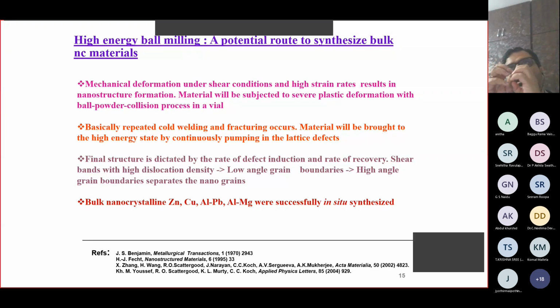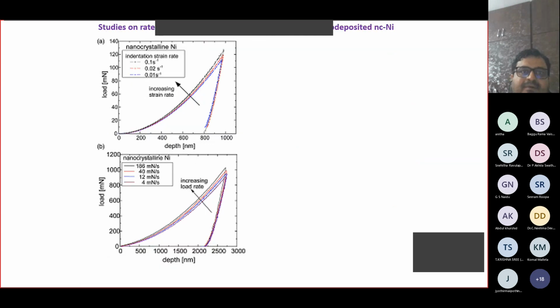As a result, you transfer some kind of mechanical energy into the powder particles, and you improve the overall free energy of the powder particles by nucleating several kinds of lattice defects such as vacancies, dislocations, stacking faults, and so on. And the free energy becomes so high that in order to minimize it and become stable, the internal structure gets rearranged by forming small nano grains. That's the mechanism of the nanostructure formation in the ball milling process.